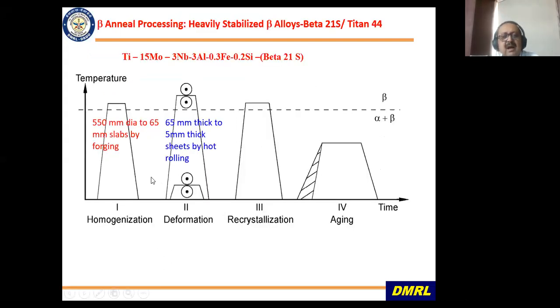So again, the beta alloys are also similarly processed. Some are beta processed, as 21S. So you have homogenization and then deformation in the beta phase field. You can also do a slight amount of alpha plus beta deformation, recrystallization in beta, and then aging in alpha plus beta to get the fine secondary alpha precipitation.